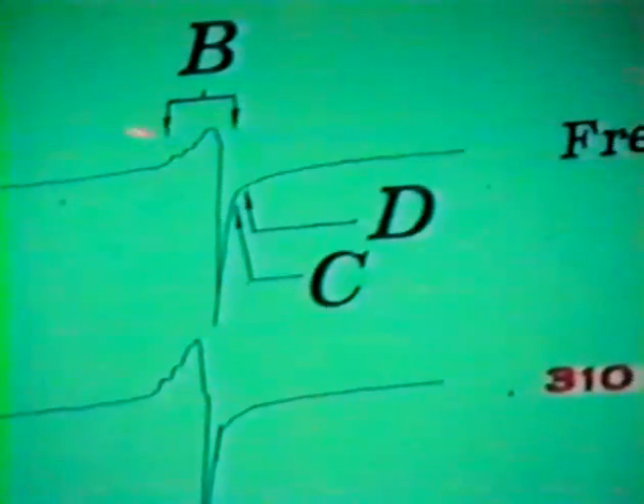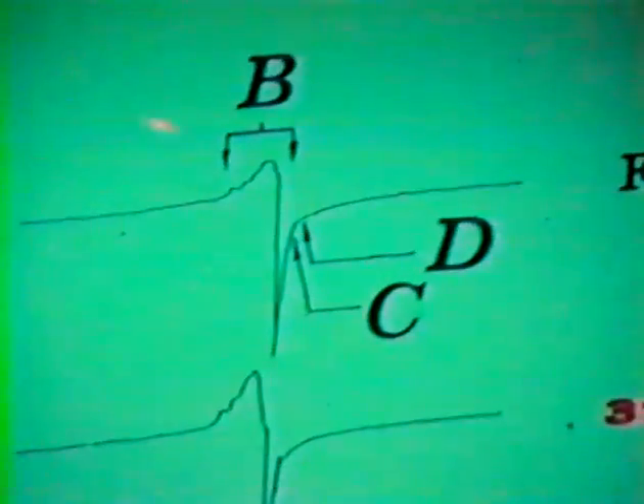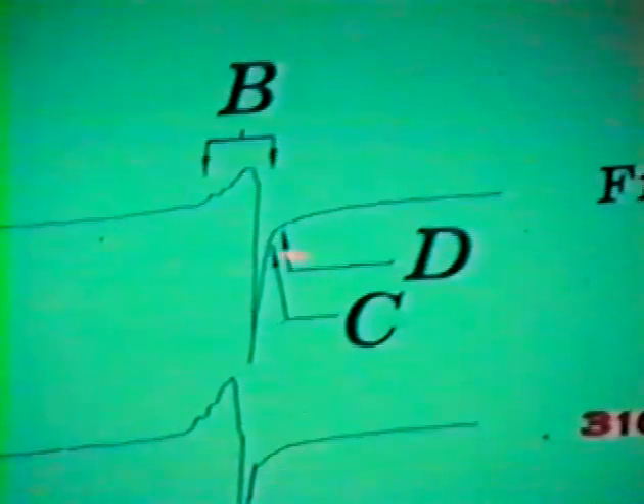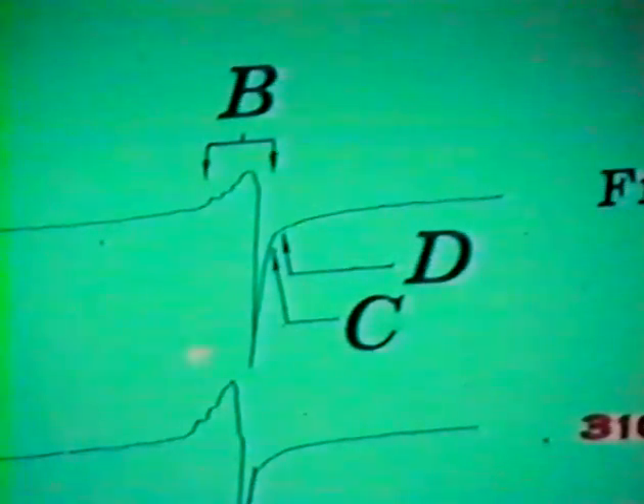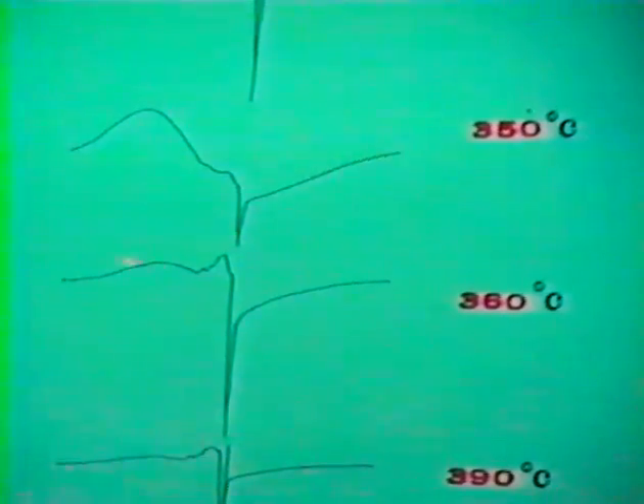That's what we expected. Okay, here for the fresh catalyst, only 3 signals occur. B, along the whole series, you can see probably is a single quartet here with the copper in axial symmetry. C and D are quite strange here, we will introduce later. When the temperature rises to over 320 degrees centigrade, another broad signal occurs, we call it A. It keeps growing as the temperature increases to 350 degrees.